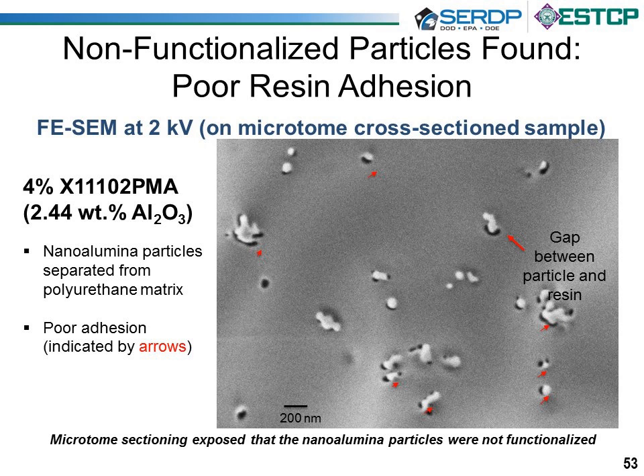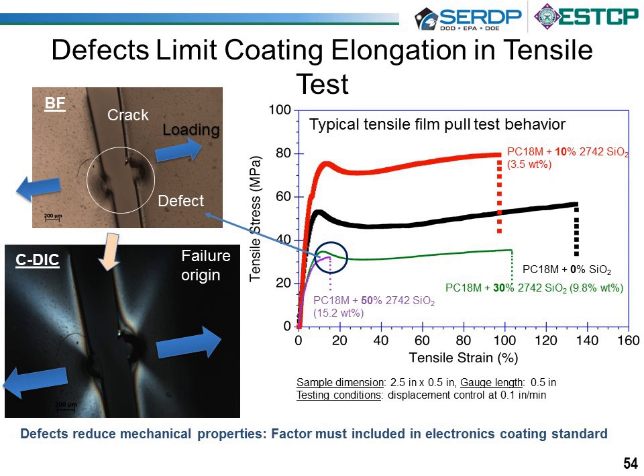And what we saw on the nanoalumina one is we saw gaps between the particle and the resin. That gap is indicative of poor bonding. In the case of the nanosilica, the particles were well adhered, and we didn't really see these gaps form. So we learned a lot. It's an observation: gaps and poor adhesion are undesirable.